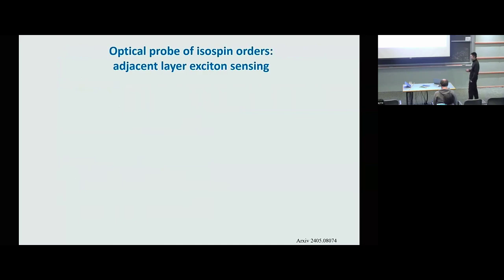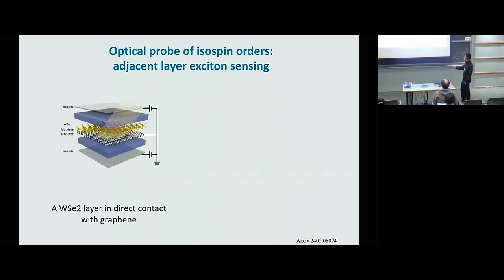And the first step is actually not that hard. It turns out we just need to take some advantage of these 2D layers, their geometry, and play some tricks with the device design. So here is the idea. It's quite simple. We just place a monolayer TMD such as WSe2 in direct contact with the graphene layers. This geometry, we have probably seen it a few times on other occasions. And there are different reasons to use this geometry, such as to introduce spin-orbit coupling. Here, it will still introduce spin-orbit coupling, but that's not our purpose. Our purpose is actually using the interaction between the graphene layers and the WSe2 to encode the isospin orders in graphene into the excitonic response, or optical response, in the nearby WSe2 layer.